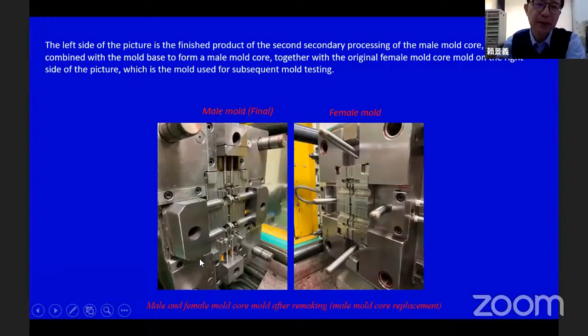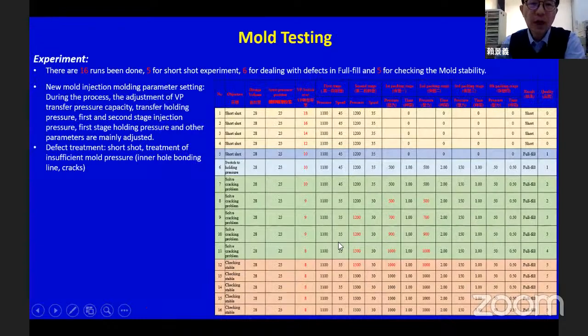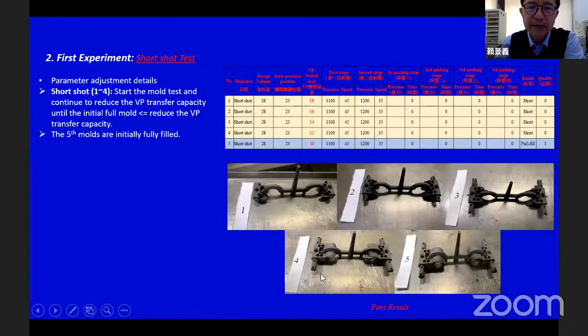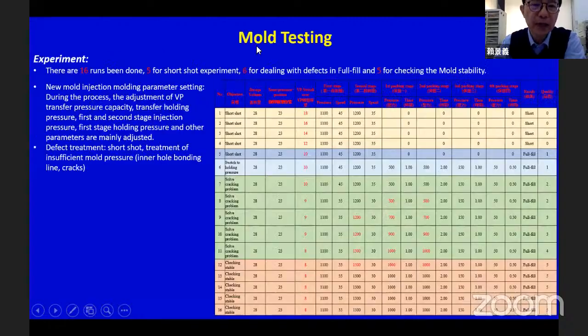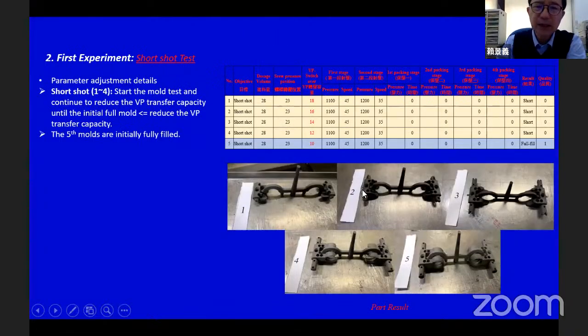Once we have the entire mold set, we perform the testing. I don't want to go into the detail. Here are some of the results for the shots. When you perform the mold testing, you need to adjust the parameters one by one, based on the previous result. Finally, we come out with a good result, and we get the optimized set of parameters for the process. Here are some of the results. We call them the shots.